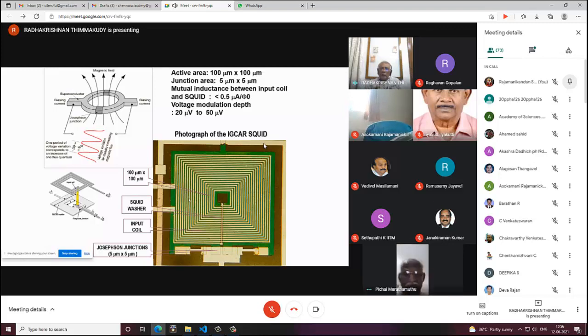And this Nb, Al2O3, Nb sandwich should not be allowed to see atmosphere during formation. So first you form niobium, then in the same chamber you evaporate aluminum, and then through a load lock you bring that out of the chamber, not to atmosphere but into another control chamber. There you give some oxygen and oxidize the aluminum. Aluminum oxide is self-limiting, it will not go into the niobium. Then you push it back into the main chamber and deposit the counter electrode niobium. And then do a lot of lithography and etching. So finally, you end up with a device.